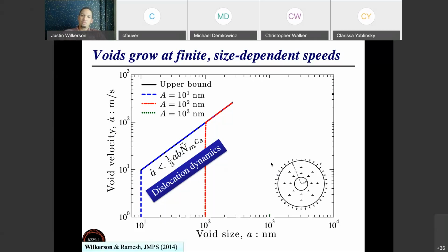So the voids are limited by this inequality here, the void rate, which tells you how fast they can grow. So basically one third of the current void size times the Burgers vector times the mobile dislocation density times the shear wave speed. That's how fast they can move. They can't move any faster than that. Okay.